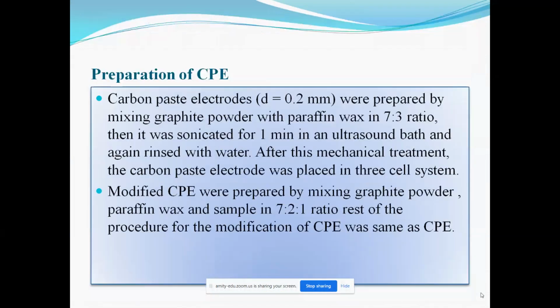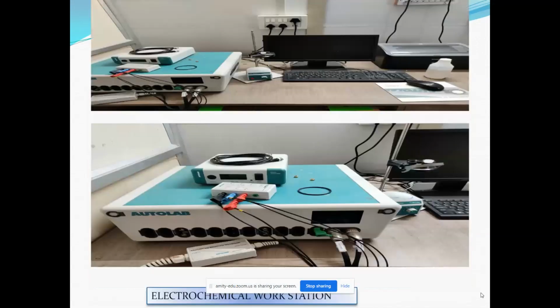Material and the electrochemical study of the synthesized compound I have done using a carbon paste electrode. The carbon paste electrode is prepared from graphite powder and paraffin wax in 7:3. When I want to modify my carbon paste electrode with my sample, I put a minimum amount of my sample, afterwards graphite powder and paraffin wax. Then I produce the carbon paste electrode so that I can use it as a working electrode. This electrochemical workstation I have used for the electrochemical study of the synthesized compound.